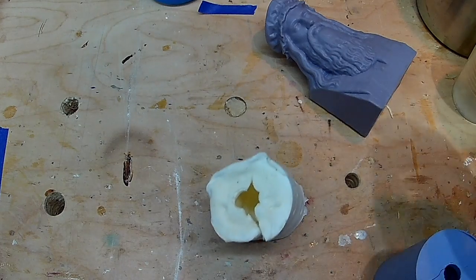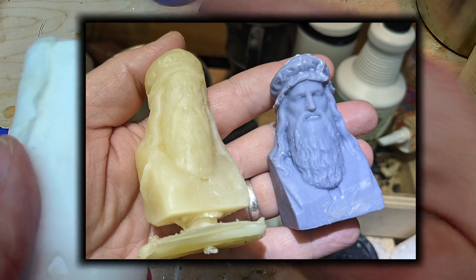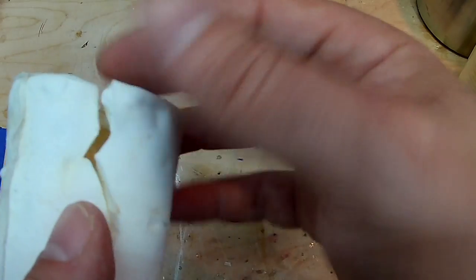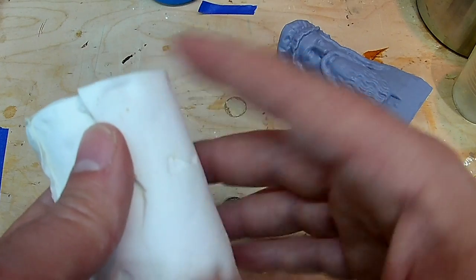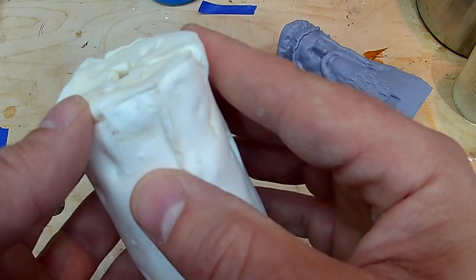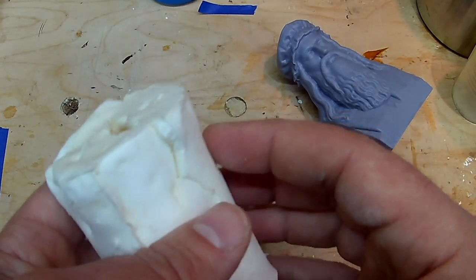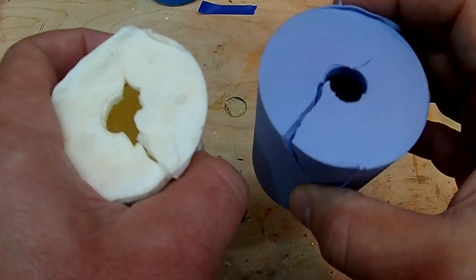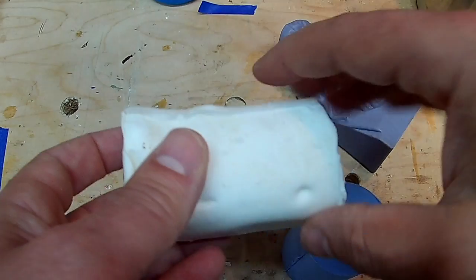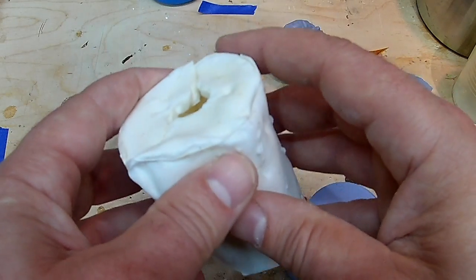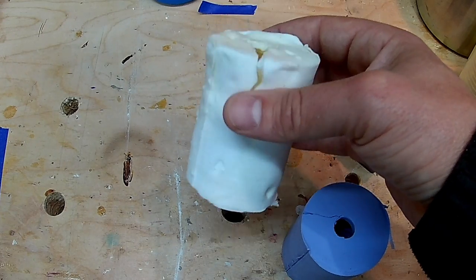So, I poured wax into it and let it set up. And when I took it out, the thing I noticed was that the wax was a little bit, I'll have a picture of it maybe, but the wax was a little bit gummy. Like it was a little soft. And as a result, if you touch it, the detail would disappear on you. Like you would basically be able to smudge the model, almost like the top layer was sort of soft. And I believe the reason is that the mineral spirits, which I had used to thin the silicone, were still present and they were leaching out of the silicone and into the caulk. And that seems pretty likely because when I left this mold for a few more days, I noticed that it had gotten smaller. So, you're probably not going to be able to tell, but this is the two-part silicone. It has retained its shape and size very well. This is the one I did. And you can maybe see there's sort of a concavity there. So, the whole thing had shrunk. And that's not surprising. Silicone caulk shrinks when it cures. And then on top of that, I'd added a whole bunch of mineral spirits and the volume of that would be displaced.